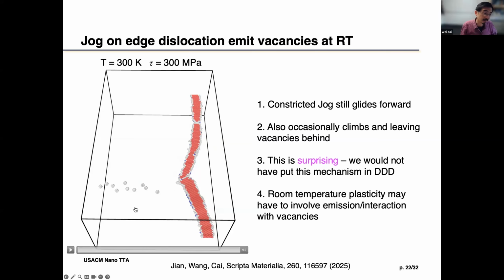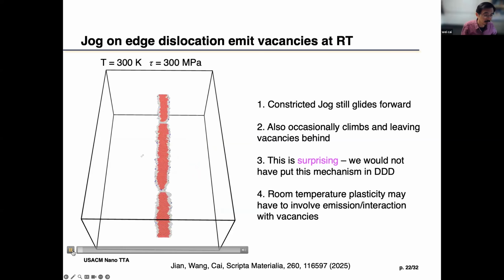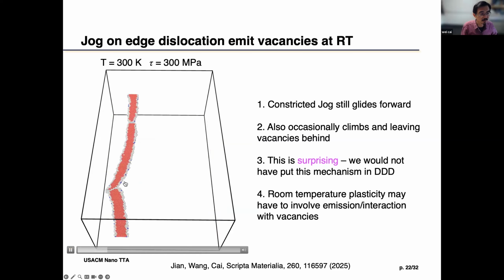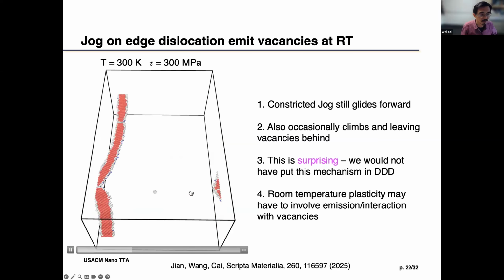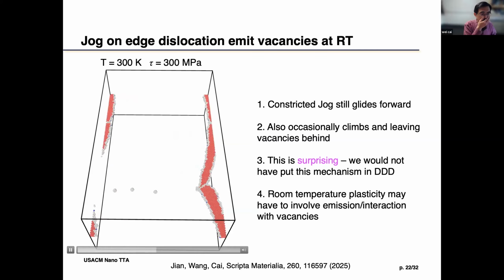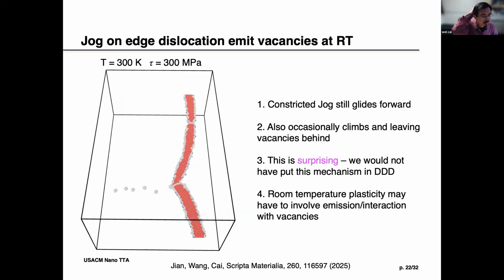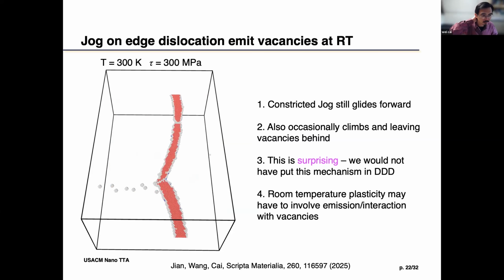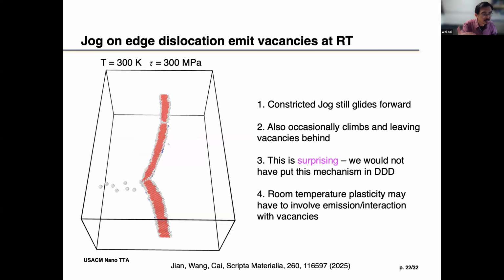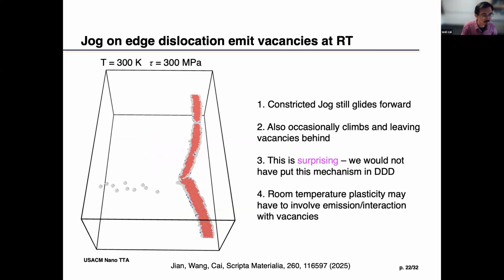But from the MD simulation, we find that the jog was moving along, but if you run the simulation longer, we find out sometimes this happens. The jog just spontaneously wants to climb along the dislocation line, and in a non-conservative motion emits vacancies. So that is very puzzling. We have an explanation of what is causing it, but if you think about it, it's very strange.